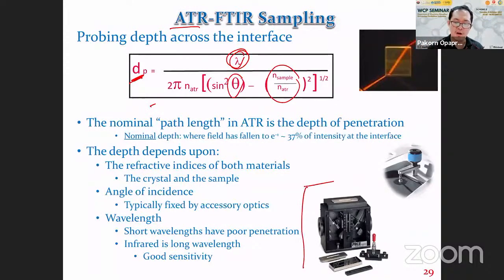So we can make an accessory that can vary the angle of the beam, in order to control how deep we want to detect in our sample. If we want to detect only the surface, we make the angle very wide. If we make the angle narrower and narrower, the beam can penetrate deeper and deeper into the sample. We can have the information that is called depth profiling information.